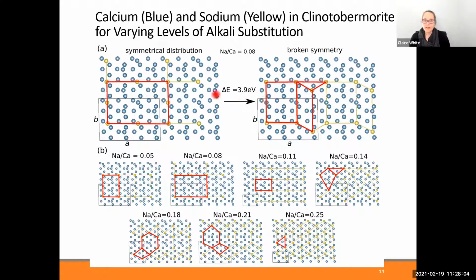And so we found that this symmetry is very important. Down here, what's shown are the most symmetric arrangements of sodium atoms in yellow, depending on the amount of sodium that's been incorporated into the system, where if all interlayer calcium atoms are replaced by sodium, you end up with this ratio of 0.25.